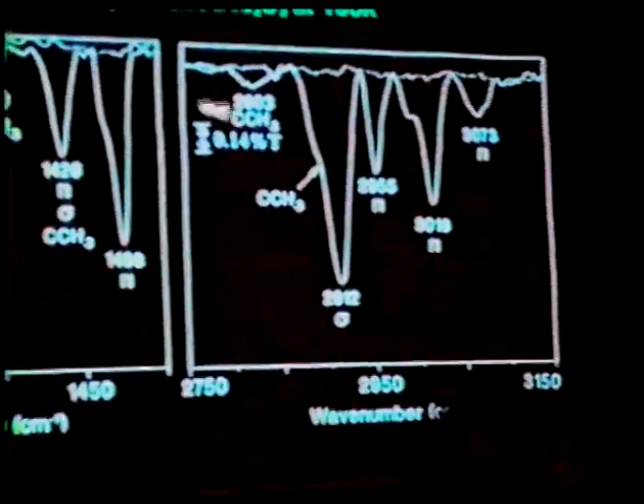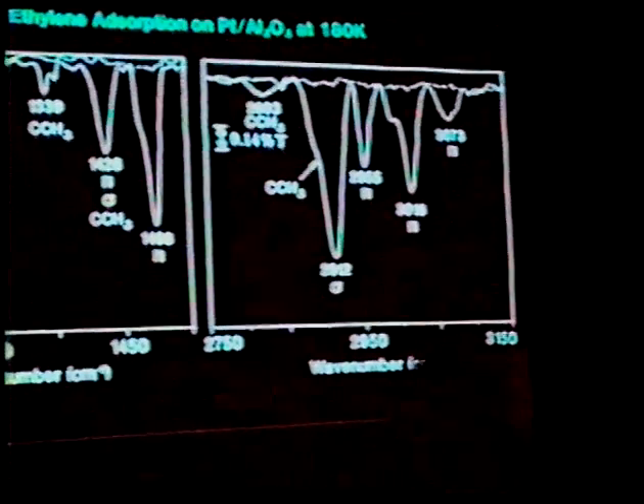All of the spectra that I will be showing you are broken up into these two categories, from about 1050 to about 1500 wave numbers, and also 2750 to 3150, because that incorporates those strong bands that we can easily identify. So here you see the strong CH stretching band from the disigma-bonded species, and you can see right on the shoulder here some formation of ethylidine, and also here there's an ethylidine-related band.